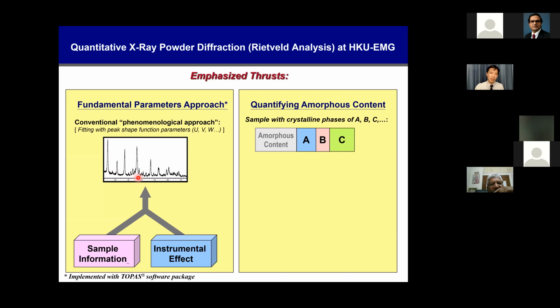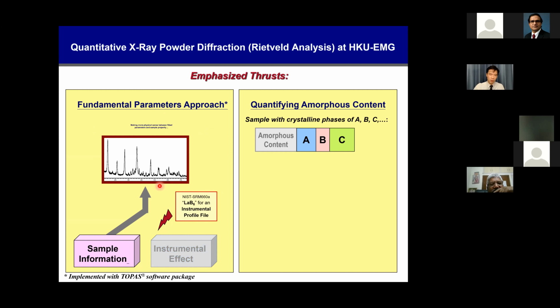So instead of the conventional approach, what you have to do to make it quantitatively reliable is the fundamental parameter approach. The way to do it is to use a standard, LaB6, to calibrate your machine to the level that you can screen out the instrument effect. So the sample profile that you have will be reborn into a new profile, and you just refine the new profile. That would make your result carry more of what we call the physical meaning of your sample structure.